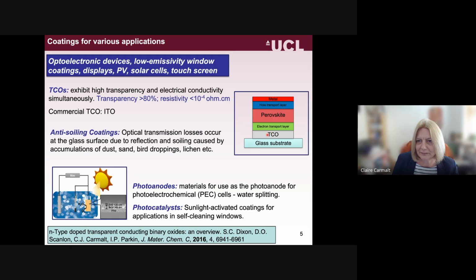We have deposited most of these layers, but obviously because time's short, I'm just going to highlight a few of them today. TCOs have been of much interest because they have this joint property of being very highly transparent, but also having high electrical conductivity simultaneously. So you're looking at transparency above 80% and resistivity less than 10⁻⁴ ohm centimetres. Now, the commercial TCO is based on ITO, which is indium tin oxide, which is really excellent, but there have been considerable concerns over the supply of indium, and so there's a lot of interest in finding alternative TCOs.